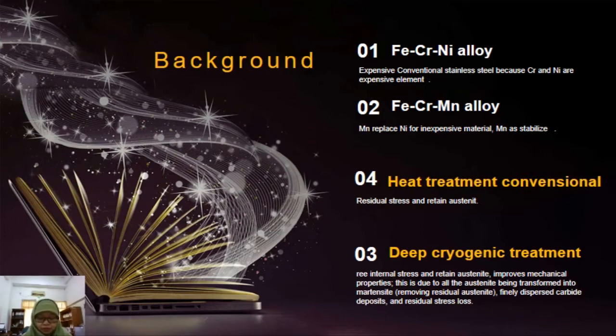Various treatments are carried out to improve the characteristics of this alloy, such as conventional heat treatment. Disadvantages of this treatment are residual stress and retained austenite. So, we developed cryogenic treatment, which is free of internal stress and retained austenite, and improves mechanical properties. This is due to all austenite being transformed into martensite. Finely dispersed carbide deposits and residual stress loss.